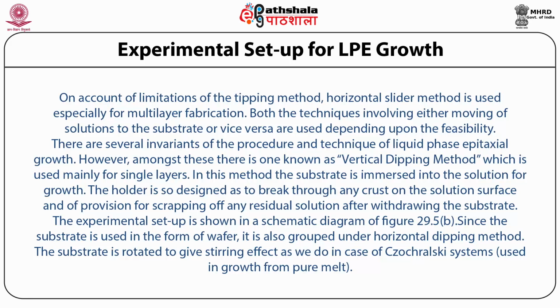There are several variants of the procedure and technique of liquid phase epitaxial growth. However, amongst these, there is one known as the vertical dipping method, which is used mainly for single layers. In this method, the substrate is immersed into the solution for growth. The holder is so designed as to break through any crust on the solution surface, with provision for scraping off any residual solution after withdrawing the substrate. The experimental setup is shown in the schematic diagram of figure 29.5b. Since the substrate is used in the form of a wafer, it is also grouped under the horizontal dipping method. The substrate is rotated to give a stirring effect, as we do in Czochralski systems, which are used in growth from pure melt.